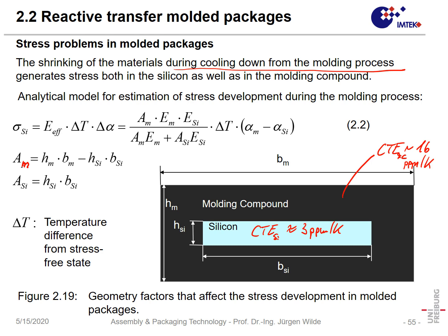And in that way, we could compute the effective Young's modulus of our system, and in that way we can say the stress in the silicon would be proportional to that geometry-dependent factor, which is influenced by the Young's modulus of the molding compound, by the Young's modulus of the silicon, by the area of the molding compound, and on the other side by area times Young's modulus of molding compound and area times Young's modulus of the silicon. Again, that's the effective Young's modulus. Here we have the delta T, and here it's the effective CTE difference.